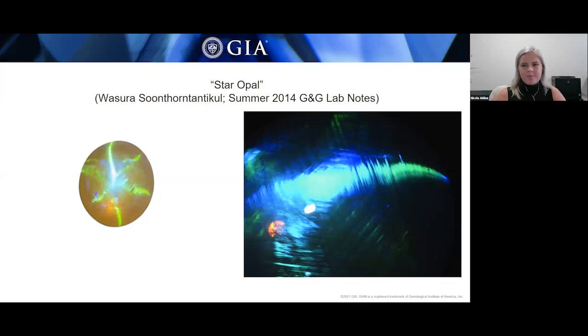And this was examined at our Bangkok laboratory. So while opal is best known for its play of color phenomenon, this opal having asterism makes it exceptionally rare. Standard gemological properties were consistent with opal, an SG of 2.1 and RI of 1.43. Under microscopic examination, this opal had parallel lines with play of color intersecting in a hexagonal pattern, and you can see that in the picture on the right.